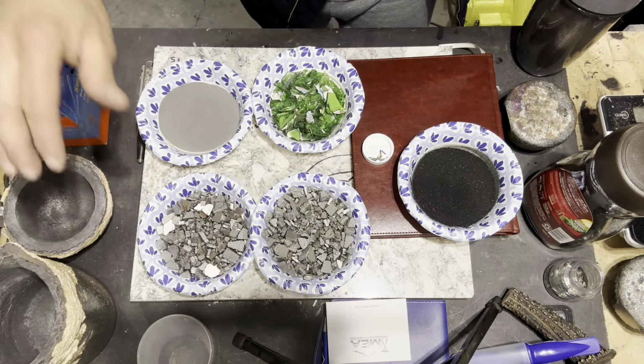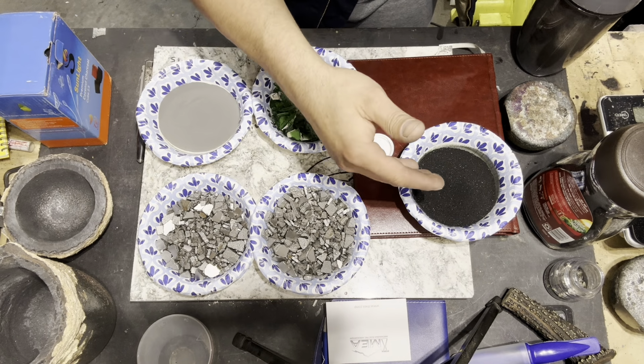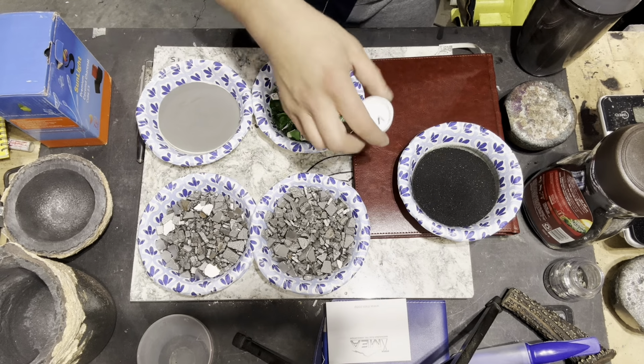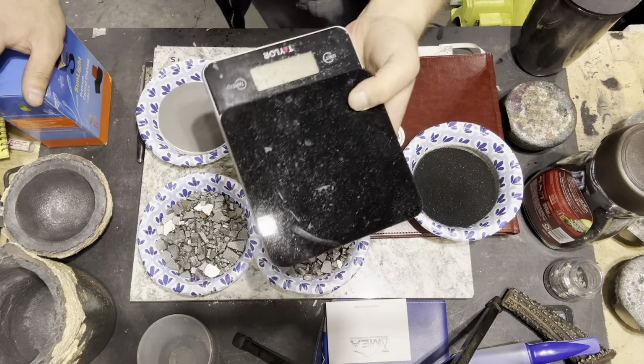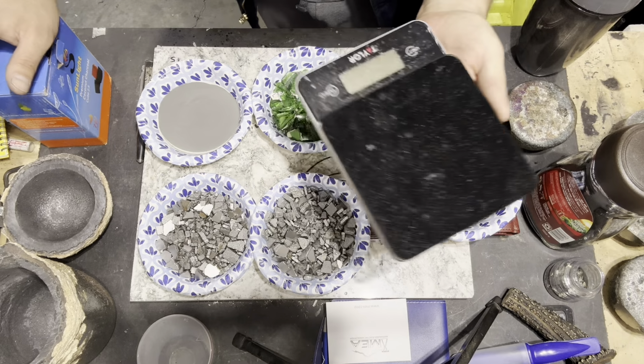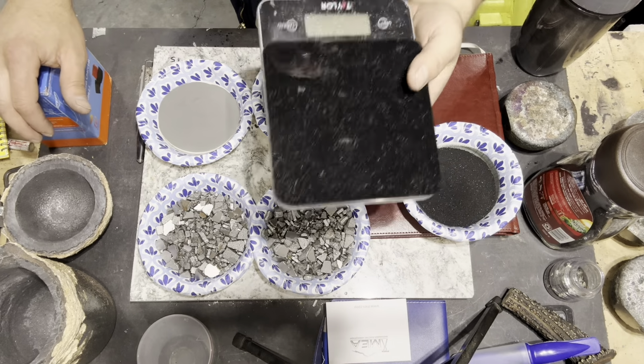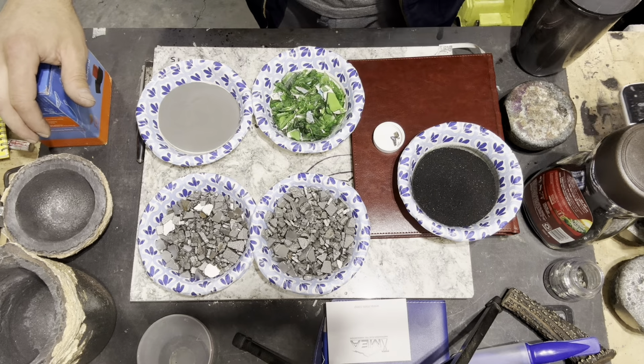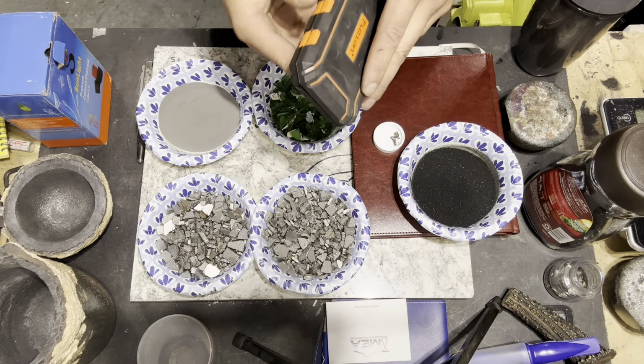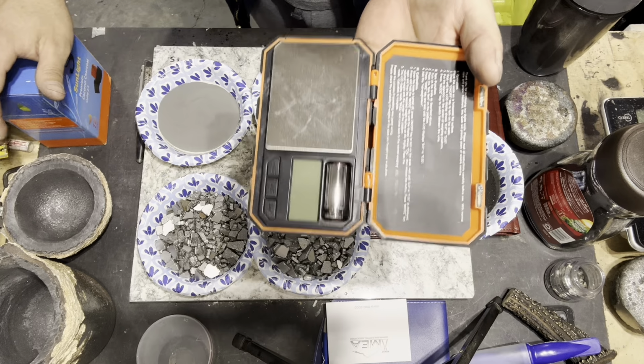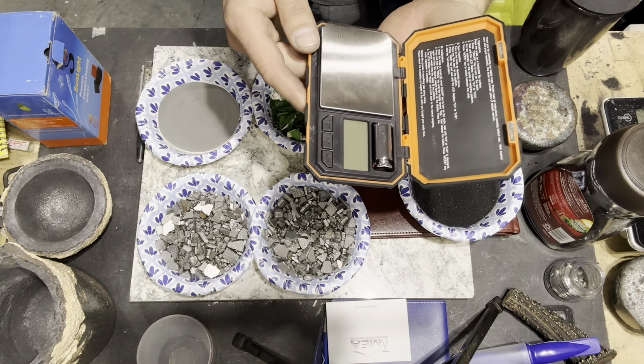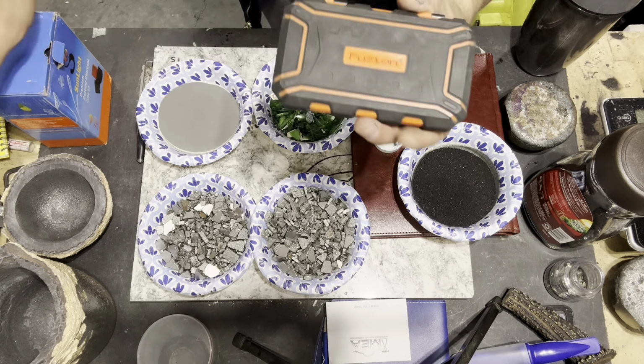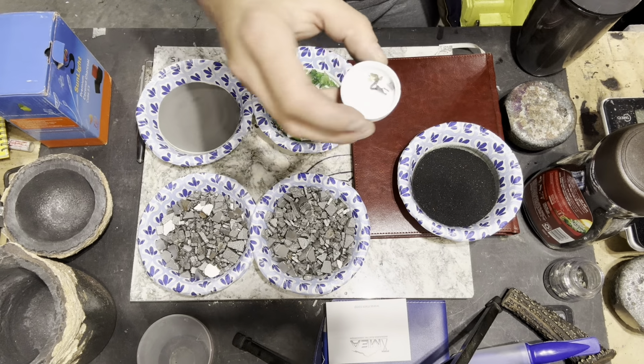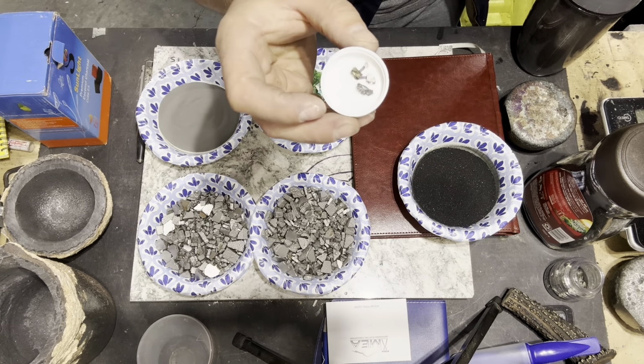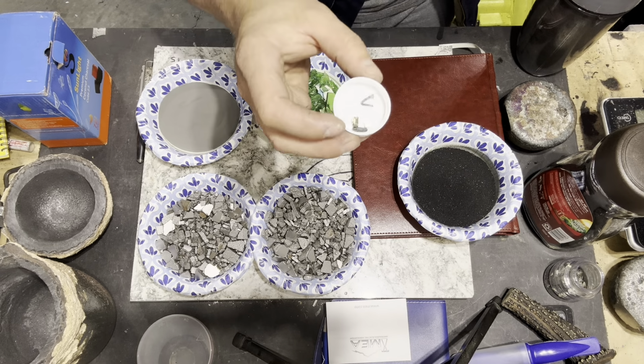Have my iron flake, the phosphorus powder, glass, carbon source, which is charcoal, and carbide former. So one thing I do is I use a little kitchen scale in grams to weigh out all my heavier material, and I have another one I use to double check. And then for the smaller gram measurements, I use one of these jeweler scales, which is actually pretty accurate, surprisingly. You can get these off of Amazon. And since I'm only using 1.8 grams of ferrovanadium, those little jeweler scales come in handy.